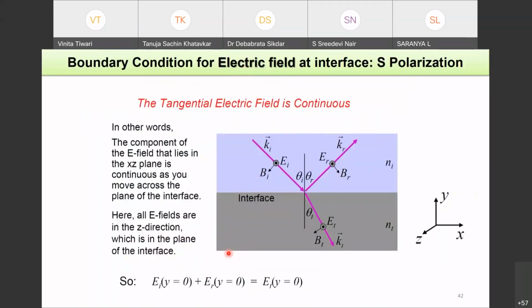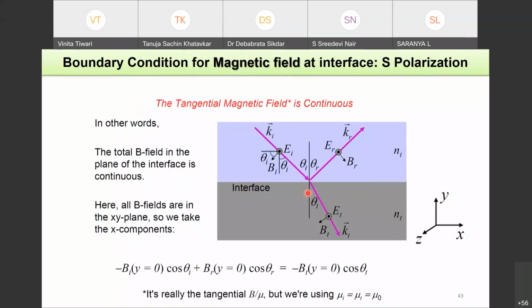So what are the boundary conditions that you have to apply at the interface? That the tangential electric field is continuous. So what is that? EI at y equals 0 plus ER at y equals 0 should be equal to ET at y equals 0. So that is how the electric field continuity works. How about the magnetic field? There also we say that the tangential magnetic field is continuous. So the tangential field, because the magnetic field direction is this way, you have to find out what is the direction along the interface. So here you can see this is minus BI cos theta I at y equals 0, plus BR cos theta R at y equals 0, should be equal to minus BT cos theta T at y equals 0.